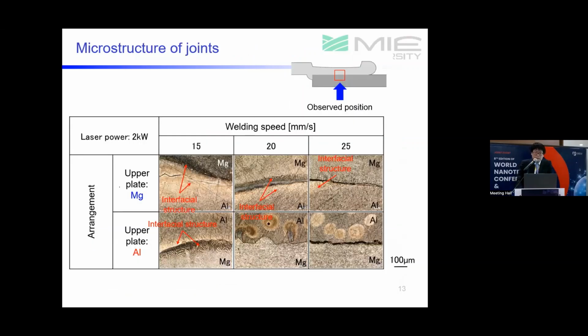The microstructure at the joint interface was observed using an optical microscope. The upper pictures show the condition with magnesium as the upper plate, and the lower pictures show the condition with aluminum as the upper plate. The observed position was the center of the joint cross-section.